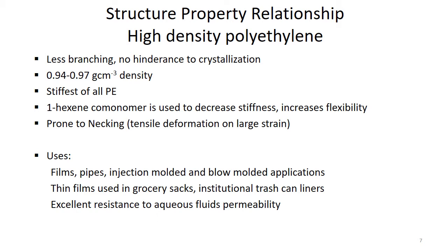If you apply a large amount of force or strain to these high density polyethylenes, they tend to go through the necking process. So what happens to them? They become white in the process due to light scattering by the empty spaces formed within the material.